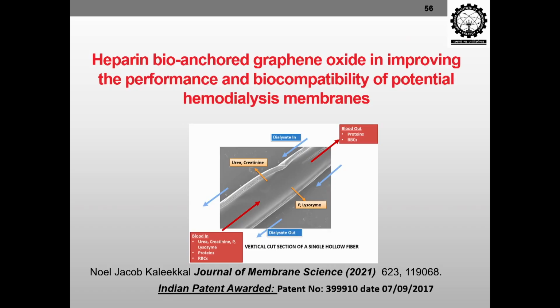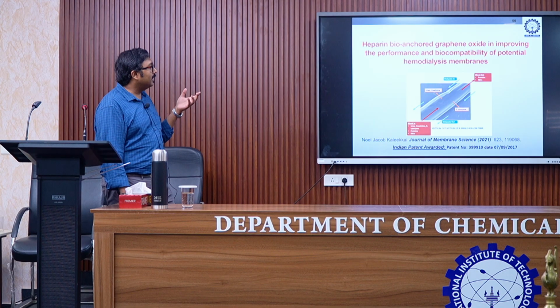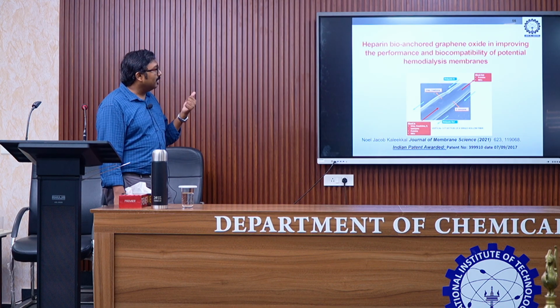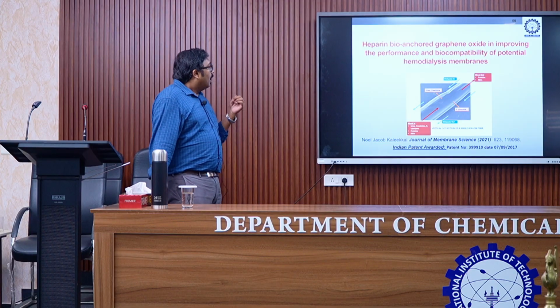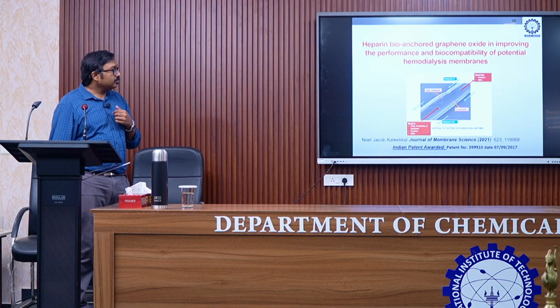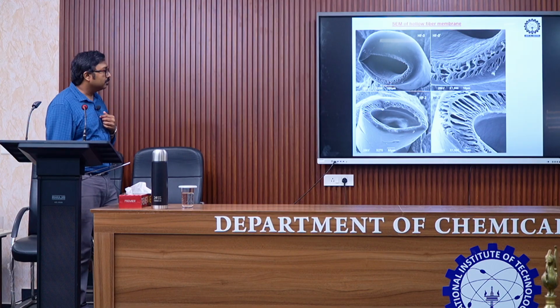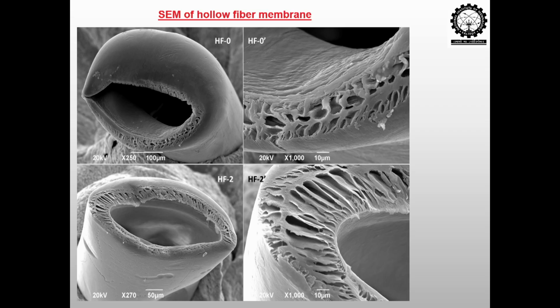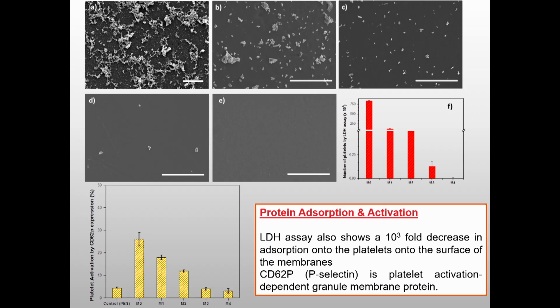So this is the last work, where we have improved the clotting time of the membranes by introducing heparin, which was bio-anchored onto graphene oxide, and that was used to make these hollow fiber membranes. This is something that we have patented. Okay, so you can see now these are the membranes. It's very difficult to take a cross section of the membrane, because the diameters are very small, around 220 micrometers, and the wall thickness is 40 to 50 micrometers.